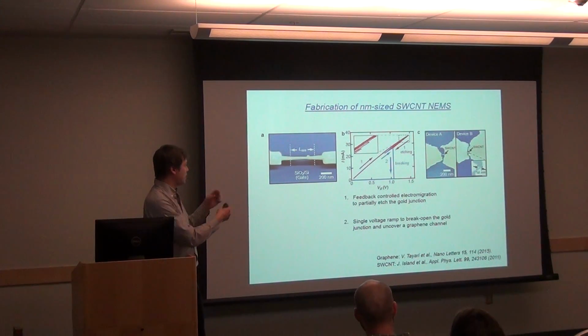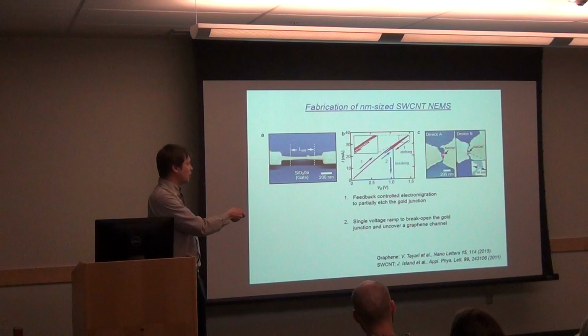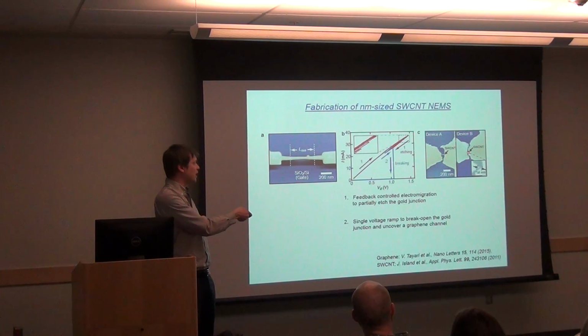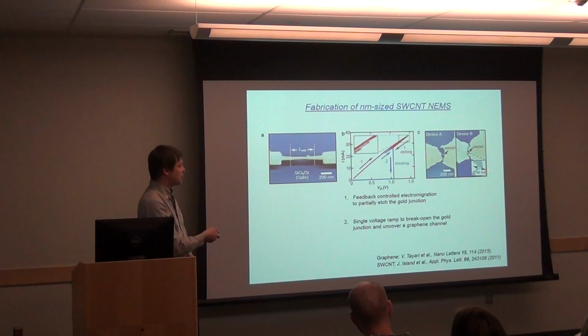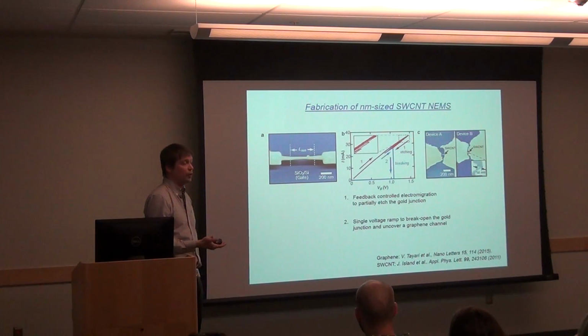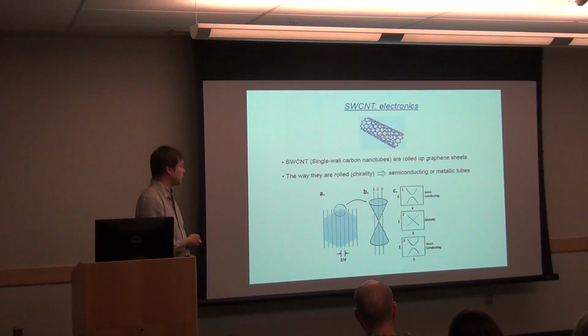With these ramps, you can etch this away into a narrow section, and then eventually decide when to break it to open up gaps at different lengths. If you use more power when you break it, you make a longer or shorter device. In this case, it was 14 nanometers, and the tubes are very strong, so they're not damaged in this process. We can do this also with graphene.